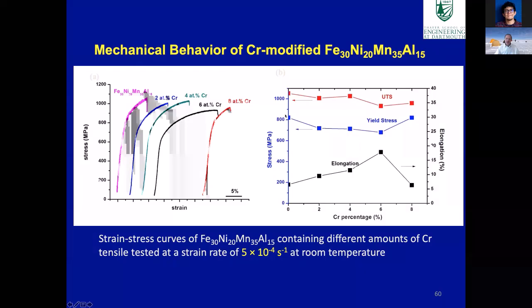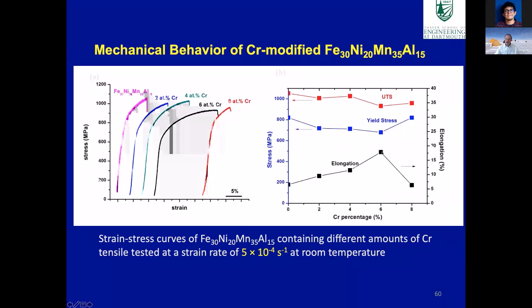So we did tensile testing. This is the high strain rate, where you don't see the environmental embrittlement so much. As you add different amounts of chromium to the material, you can see the yield strength goes down a little bit until we change the microstructure at 8% chromium. But if you look at the elongation, which is indicated on the right axis, as you add different amounts of chromium, the ductility slowly increases in the material until we change the microstructure. So what the chromium does is actually improve the ductility of the material.